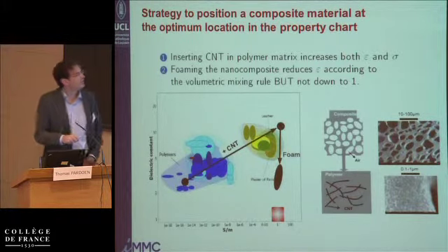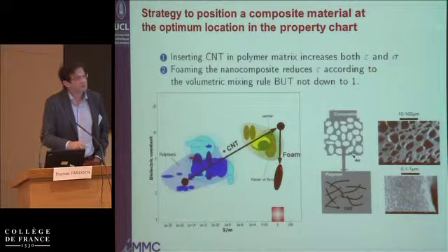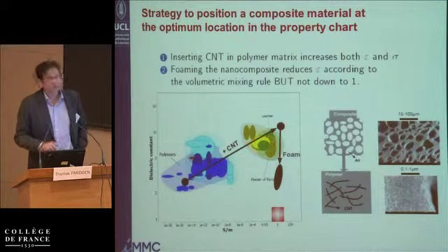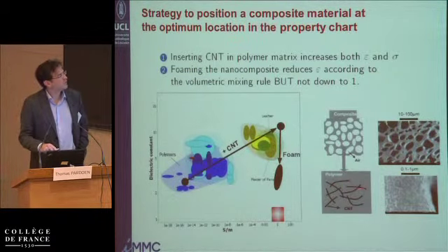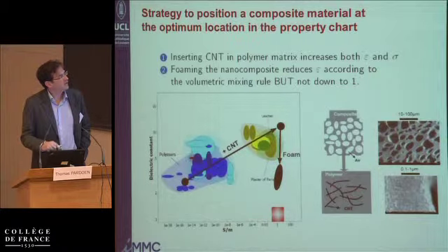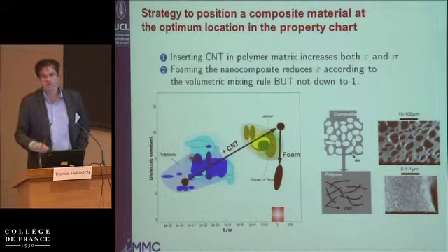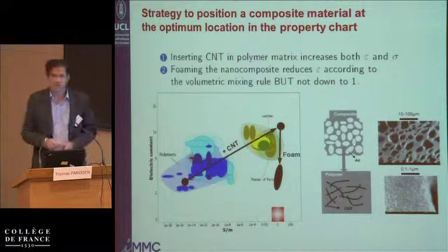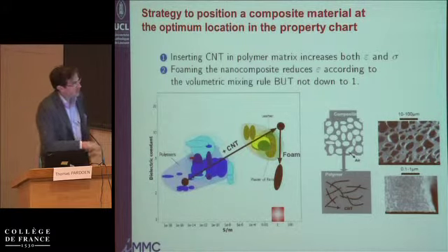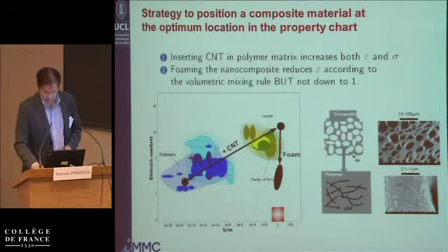So in order to reduce the dielectric constant, the idea was to foam this nanocomposite. So mix of polymer and nanotubes, then foam it, and by just a law of mixture, you're reducing the dielectric constant. Not to 1, unfortunately, but 2 or 3, depending on the material.